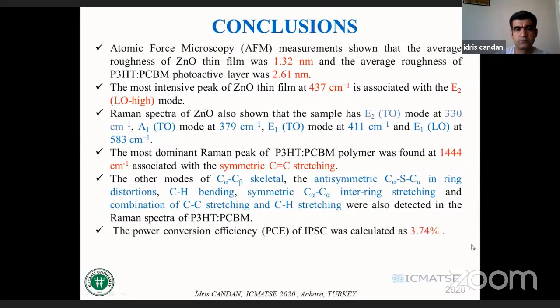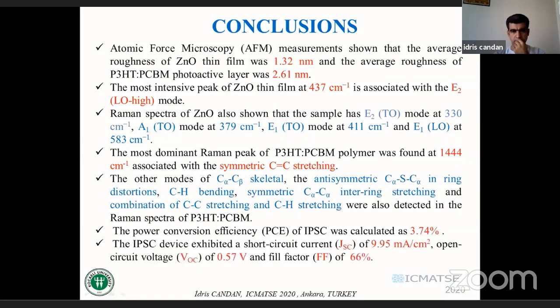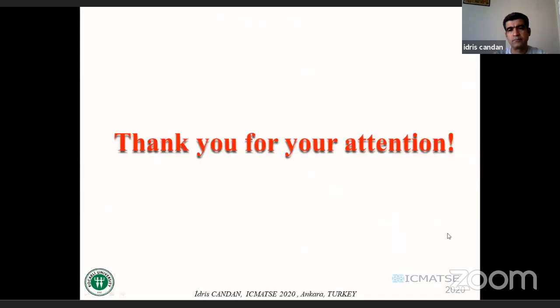The power conversion efficiency of the inverted polymer solar cell was calculated as 3.74%. The inverted polymer solar cell device exhibited a short circuit current of 9.95, open circuit voltage of 0.57 volt, and fill factor of 66%. And thank you for your attention.